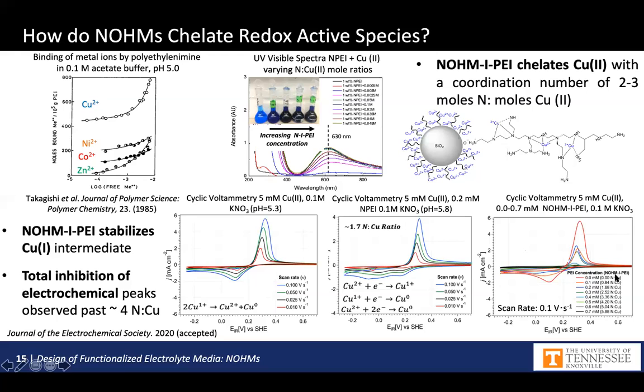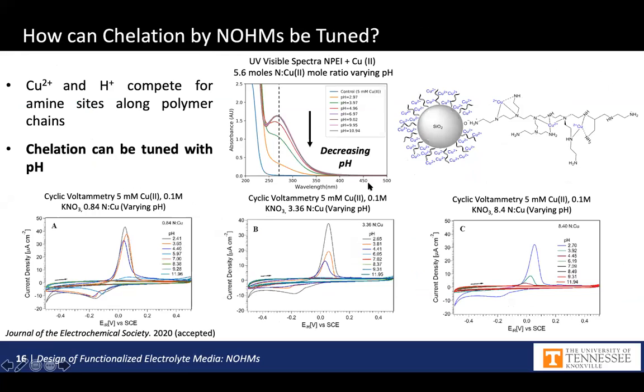So we began to think about how we can tune that chelation to actually harness those redox active molecules. On the next slide, we studied the effect of pH in solution. If you look at the top UV visible spectra here, you can see that this peak that gives the characteristics of those complexes is decreasing in intensity as we lower the solution pH. So we began to think that the copper ions and the protons are competing for those amine sites along the polymer chains. We began to think of chelation being tuned by the pH, and we can think of things like a pH swing to catch and release redox active species on electrode surfaces.